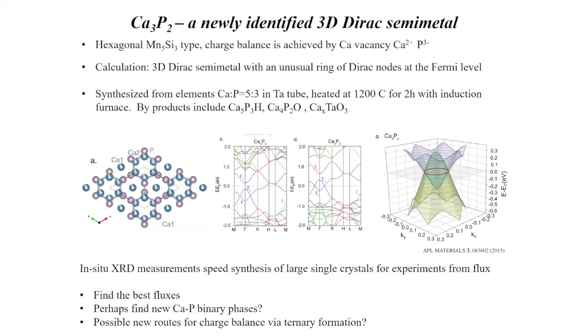And so our idea was that we would try to grow this from flux instead of by solid state reaction, because this is a good route to make large single crystals. The idea from flux is that you would dissolve the calcium and the phosphorus into some low melting point compound, maybe a metal, maybe a salt, raise the temperature to get a homogeneous melt, and then slowly lower it so that the crystals would drop out of solution. Exactly like growing sugar crystals from a saturated solution of sugar and water.